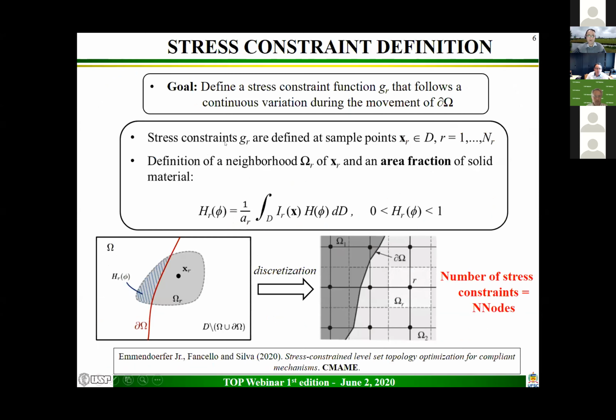So the goal is to define a stress constraint function that follows a continuous variation during the movement of the boundary. So we define a finite number of stress constraints in the so-called sample points. We also define a neighborhood around the sample point, and also an area fraction of solid material in this neighborhood, which is given by this integral. In this work, the sample points are the nodes of the finite element mesh, and the neighborhood is a square area of the same size of the finite element size.